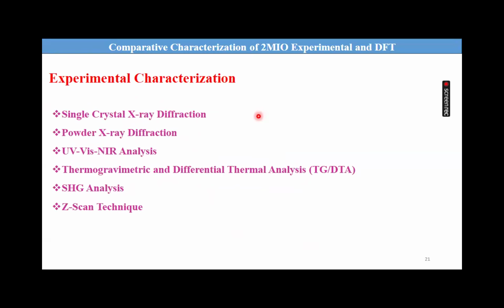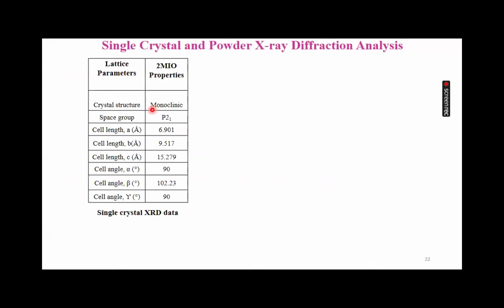Comparative characterizations of 2MIO, experimental and density functional theory. We have focused on 2-methylimidazole oxalic acid with experimental characterizations such as solubility characterization, single crystal X-ray diffraction, powder X-ray diffraction, UV visible NIR analysis, thermogravimetric and differential thermal analysis, SHG analysis, and the Z-scan technique. Single crystal and powder X-ray diffraction analysis: the obtained lattice parameters of 2-methylimidazole oxalic acid confirmed a monoclinic crystal structure with space group P21.